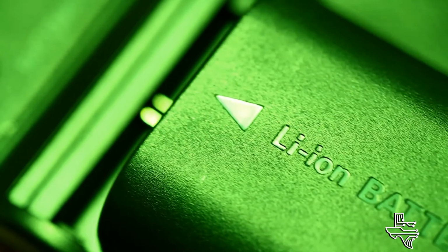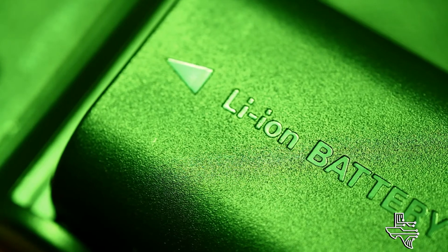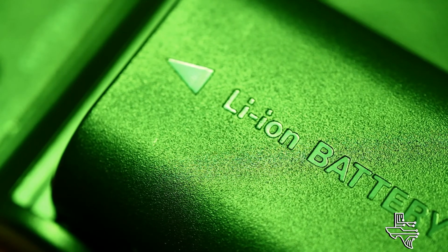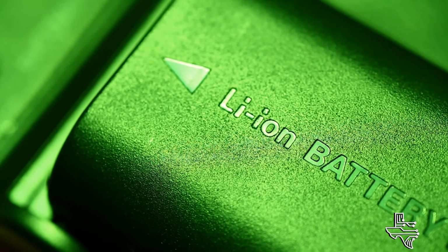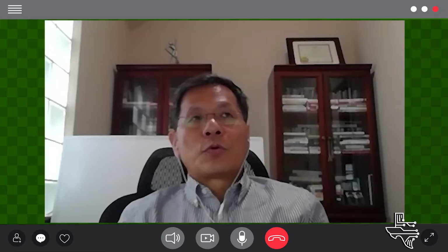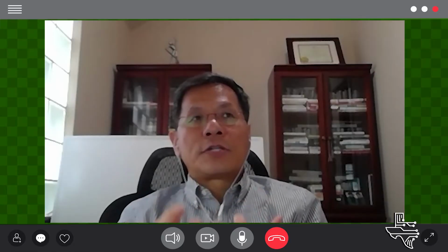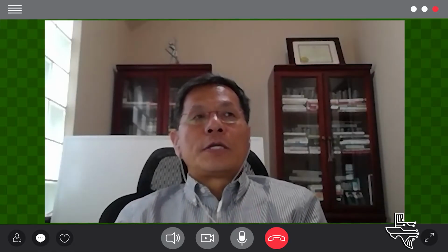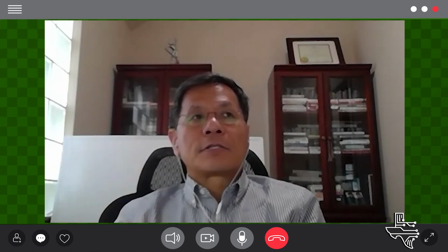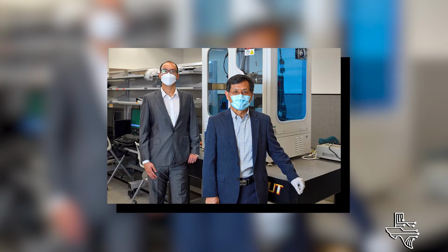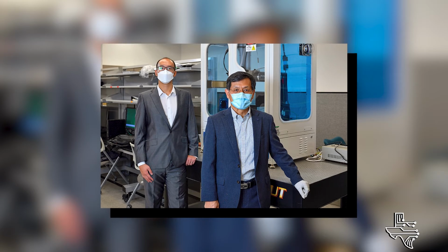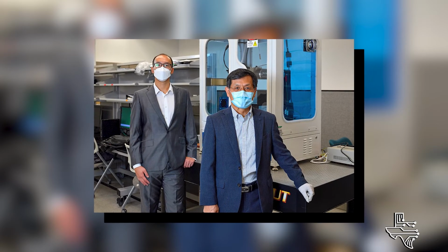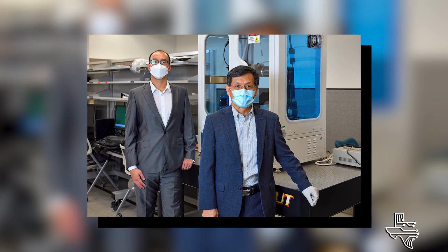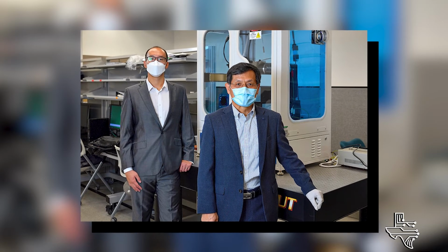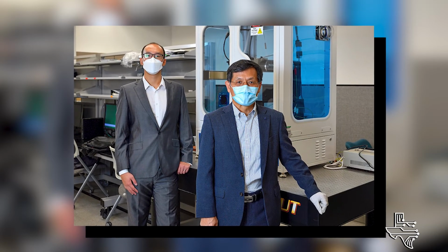In addition to this, we need to increase the sulfur loading and also stabilize the sulfur on the cathode side. We introduced a carbon nanotube 3D structure. In our lab, we grow a 3D carbon nanotube and incorporate sulfur in it. We stabilized it and increased the efficiency of this cathode. So altogether, we produced a very high energy density in the lithium sulfur battery.